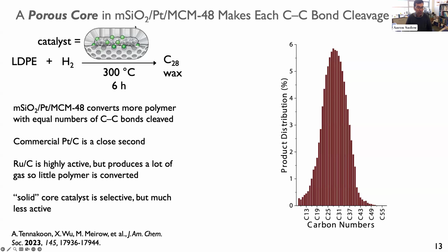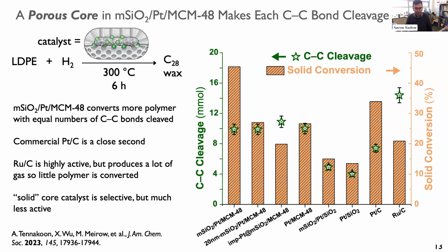And the idea here was, well, the polymer could come in, get cleaved, and then find its way out through other pores through the center core. And that has a remarkable effect of allowing us to get to longer chains in a really rather Gaussian, quite nice distribution. It decreases the gas formation because we don't have very much tailing into the low molecular weight. And it gives really quite high activity for conversion.